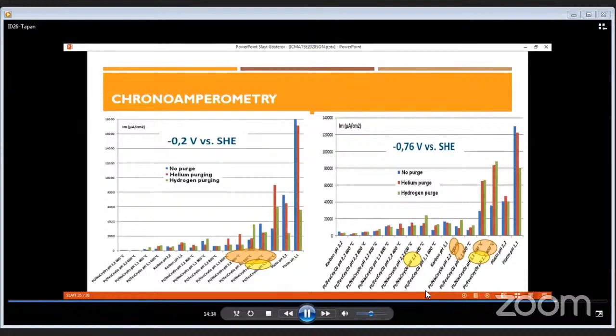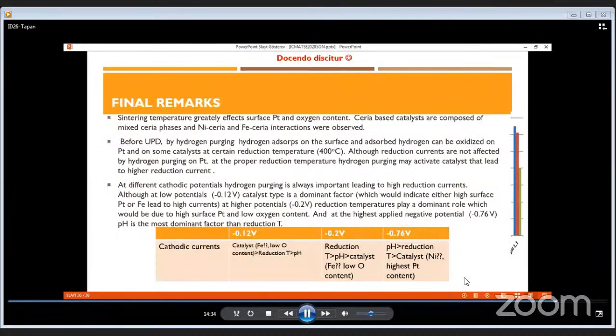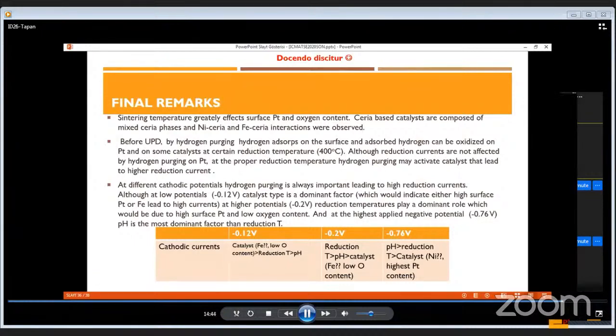As a final remark, sintering temperature greatly affects surface platinum and oxygen content. Ceria-based catalysts are composed of mixed ceria phases, with nickel ceria and iron ceria interactions. Before under-potential deposition by hydrogen purging, hydrogen adsorbs on the surface, and adsorbed hydrogen can be oxidized on platinum on some catalysts at certain reduction temperatures. At different cathodic potentials, hydrogen purging is always important, leading to high reduction currents.